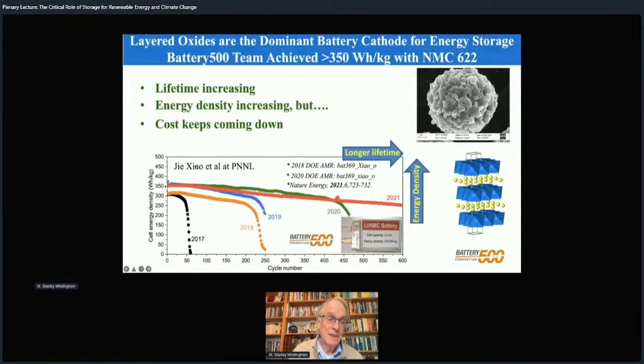So this is the data. This is an ex-PhD student of mine, Jay. And you can see how we progressed the number of cycles over the years. We started out at 300 watt hours per kilogram. Over here, we're now at 315. As of today, I think we've got over 800 cycles out of this at 350 watt hours per kilogram. And we've got roughly 100 cycles now out at 400 watt hours per kilogram.